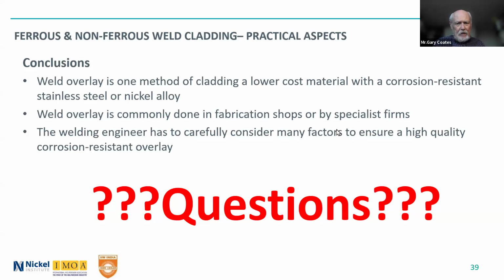What about distortion in the weld overlay case? Yeah, well, you can't weld overlay, let's say, a 3 millimeter thick piece of plate without getting distortion. Obviously you want to reduce the amount of heat input going into it on thinner material, but yes, you may need to straighten it out afterwards. Not so difficult with a flat piece. If you got a formed piece, that could be difficult, but yeah, distortion is a potential issue on thinner sections there, and just like it is when you're welding two pieces of plate together, distortion can be an issue there.